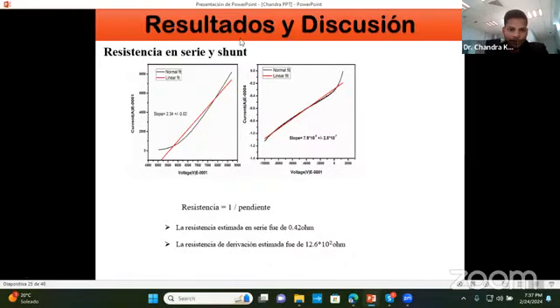Here we have calculated the series and shunt resistance through the slope that I discussed earlier. Always keep in mind the value of series resistance should be less than 1. If you are designing a better device, then you have to keep the total series resistance, or sum of series resistance, less than 1. And the parallel or shunt resistance should be higher. If shunt resistance is higher, it minimizes the rate of leakage current or minority current. And this resistance should be lower: if the resistance of material and resistance of contact is less, then sunlight can easily reach the depletion region or depletion layer.